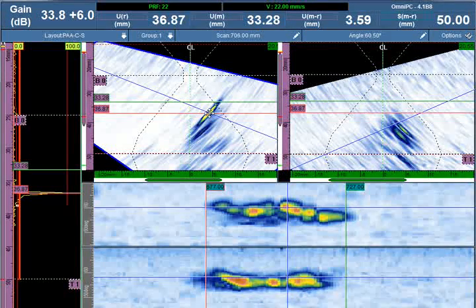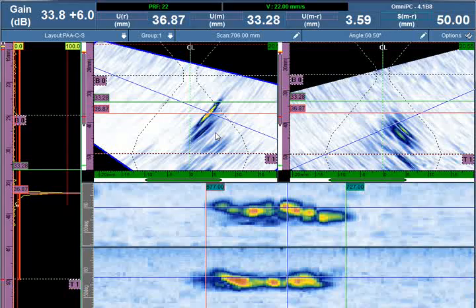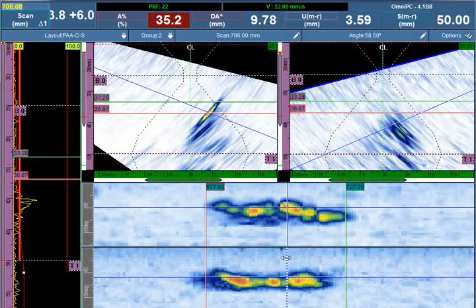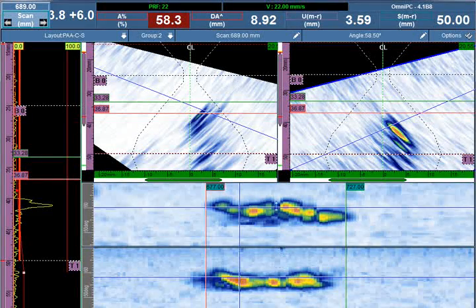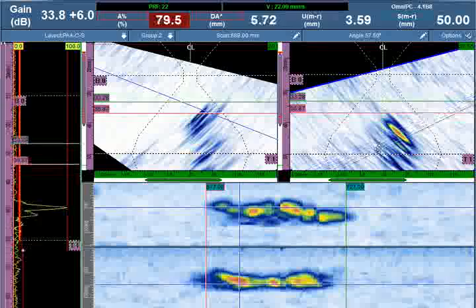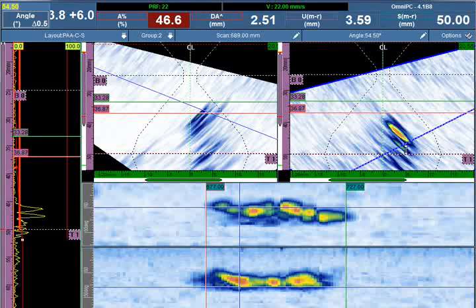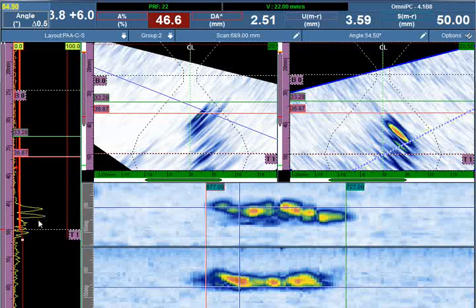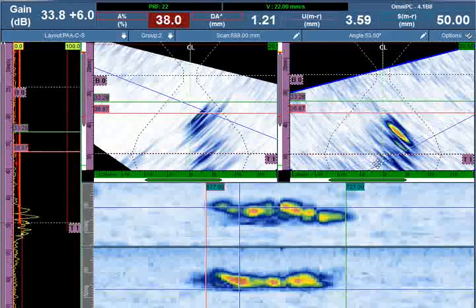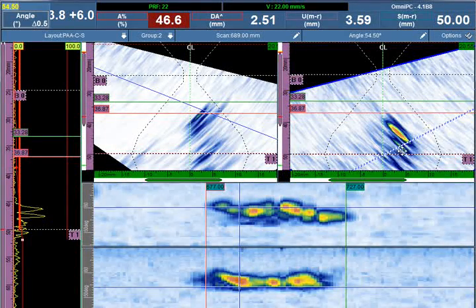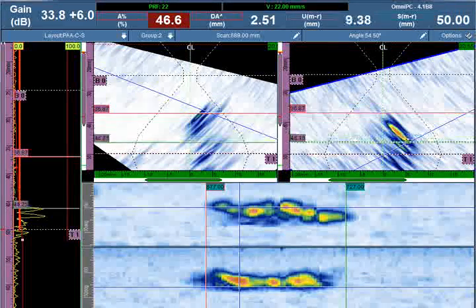We're going to identify the tip center energy based on the color palette of the signal. We've identified the deepest, or the bottom of the crack, and will now identify the top of the crack. That occurred at scan axis position 689, and here's the tip-diffracted signal — it's not connected to the outside surface. I can see the crack geometry as I move the A-scan through the S-scan, and I'm going to identify the center of the deepest tip with the second measure cursor.